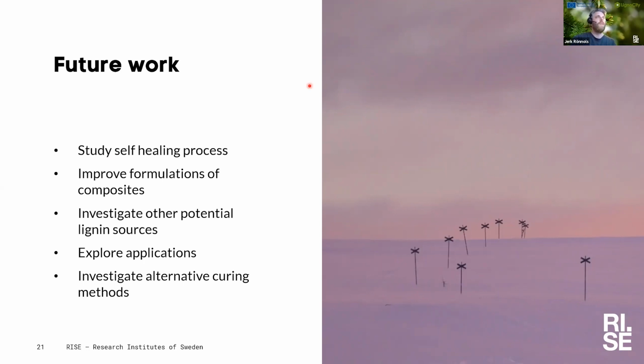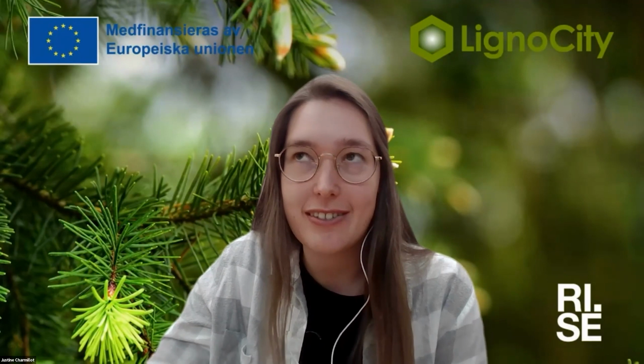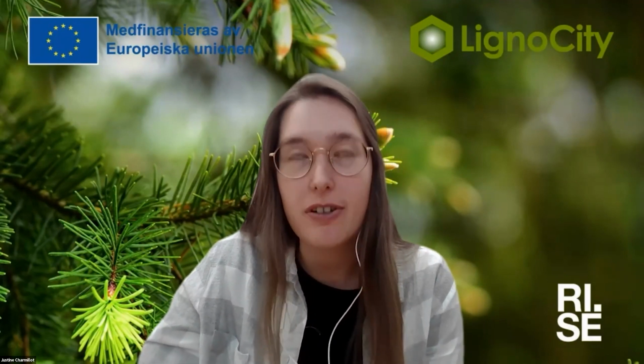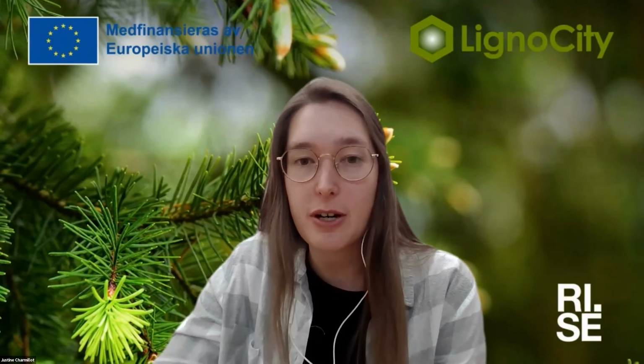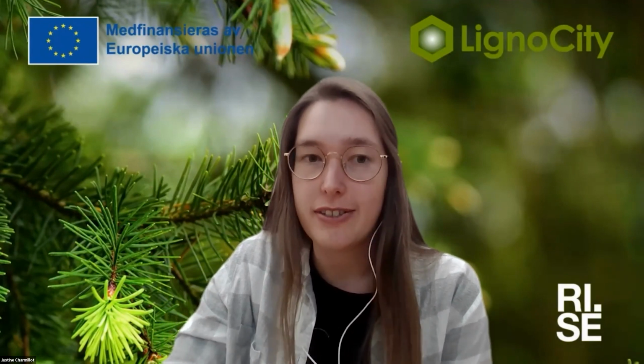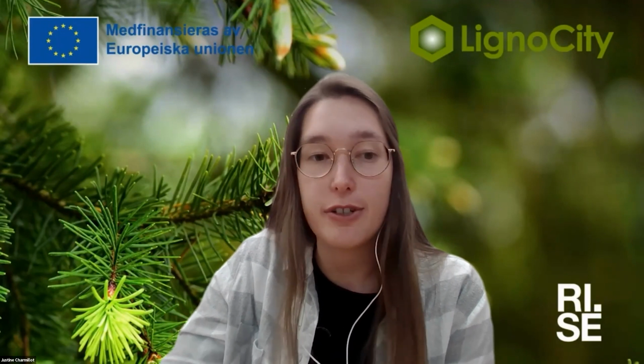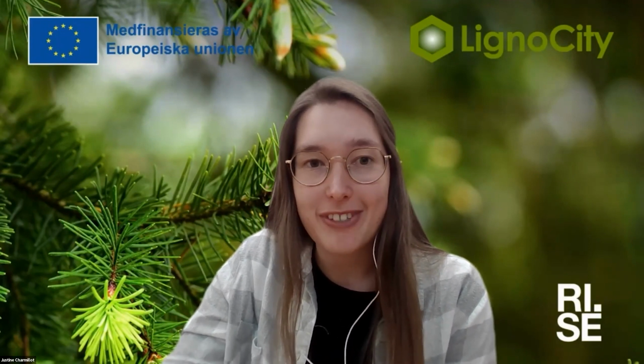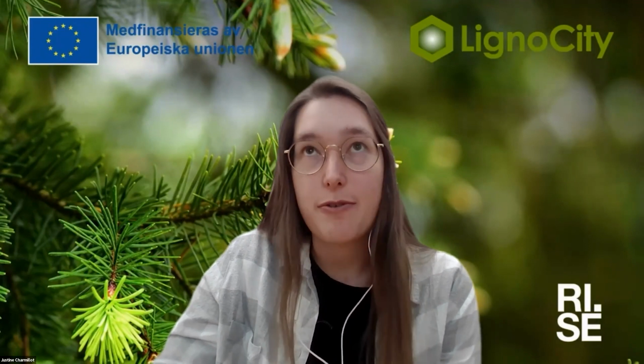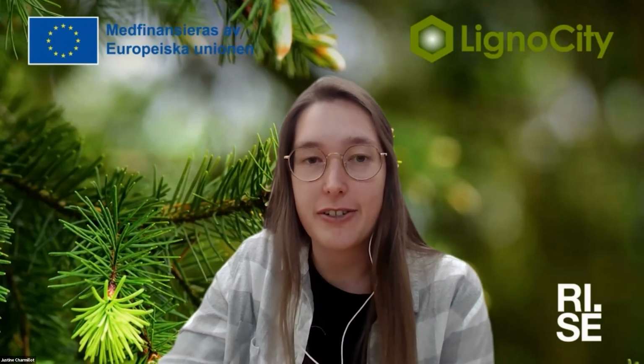Well, typically, my organic chemistry background says that under aqueous acidic conditions, you will hydrolyze the acetals. For these, I do not know. Maybe Justine is better suited to answer this question. Yeah, as you said, under acidic aqueous conditions, those acetals are typically not that stable. However, for neutral conditions, they are quite stable. I don't know exactly the influence of the chain, the distance, but as a rule of thumb, they tend to hydrolyze under acidic conditions.